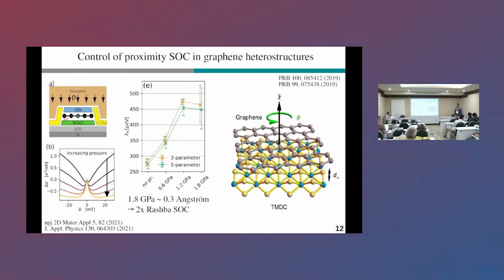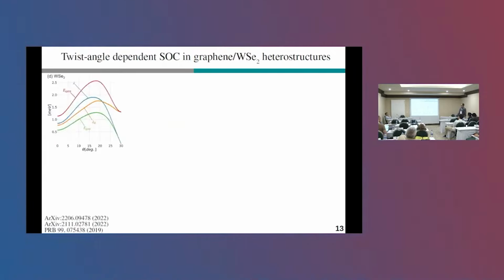And now the second thing that can be done is, of course, twisting. The recent tight binding calculations have shown the following. When you place graphene on tungsten diselenide, the valley-Zeeman spin-orbit coupling in graphene will follow this blue line. We have this intermediate maximum at around 15 to 20 degrees of the twist angle, and it then goes to 0 at 30 degrees, which is due to symmetry.